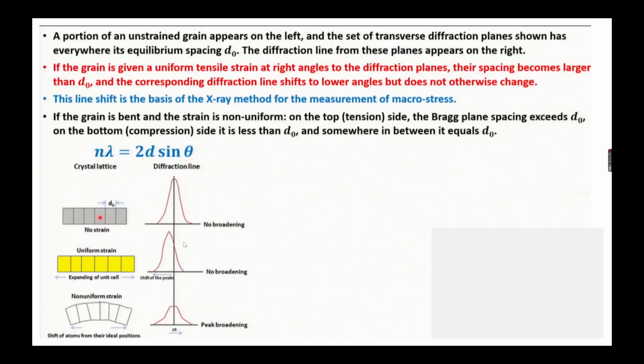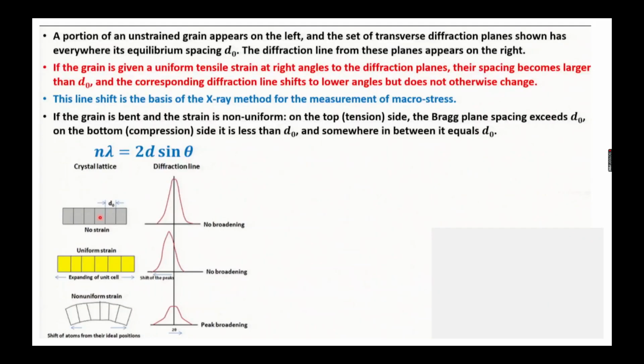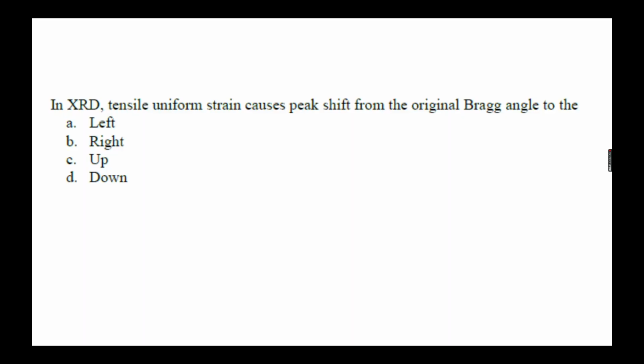Line shift is the basis of the X-ray method for the measurement of macro-stress. So when you have a stress or strain applied in your sample, depending upon the type of strain, whether it is uniform or non-uniform, you will get either a peak broadening or a shift in the peak. So the answer is A, left.